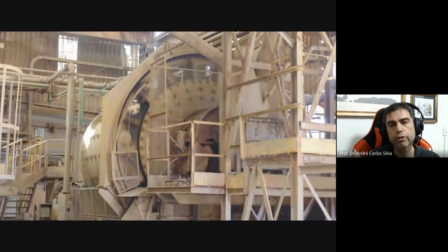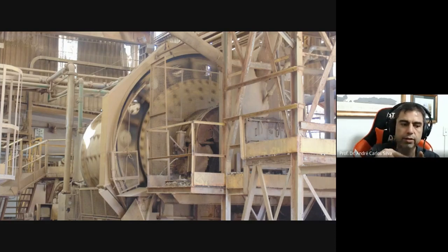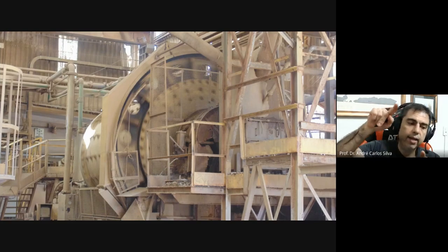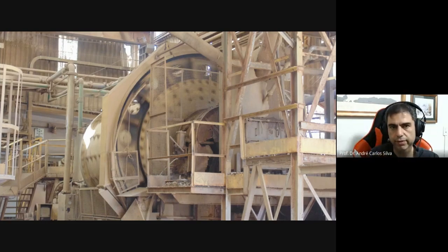Okay, so instead of losing the whole body, losing your alloy, and having micro fractures of the mill, you put the liners, and the liners can do the trick. Okay, the liners also help you with another thing, which is the trajectory that you want the grinding media to have inside of the mill. You need the grinding media to reach a certain height and then fall. And by doing this, you have the breakage of your material, okay? And the liner can help you with that.